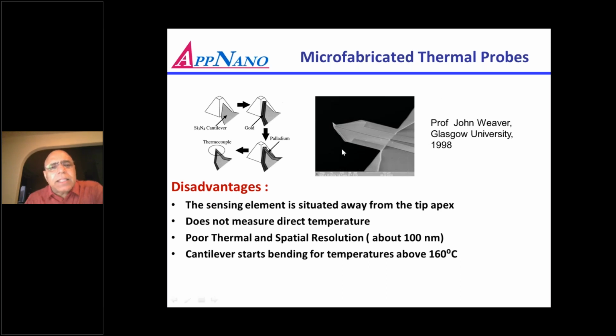These probes are basically silicon nitride. If you see this image, there is a silicon nitride cantilever, and the metal is patterned on top of this to make a thermocouple. So what they do is make a pyramid, and in this pyramid, the silicon nitride cantilever is patterned. One of the problems with this technology is that since the lithography is on a pyramid, it has to be done with e-beam lithography. This probe requires at least 4 or 5 steps of e-beam lithography, and that makes it very difficult to make in a simple microfabrication factory.